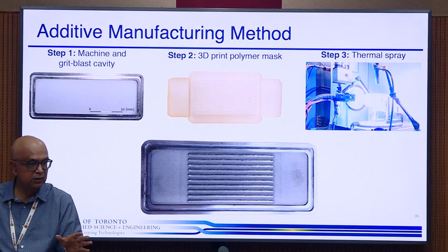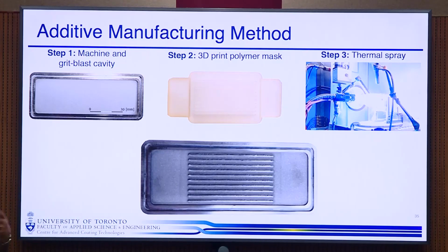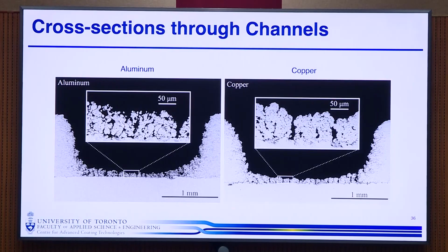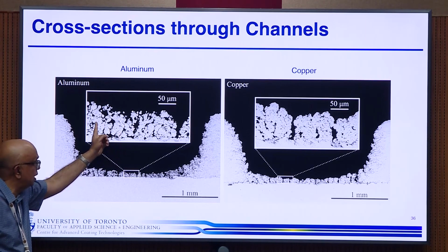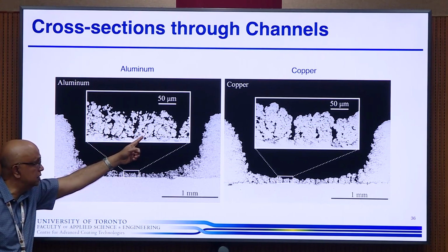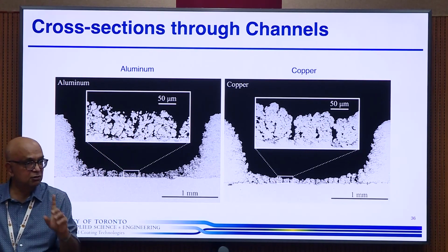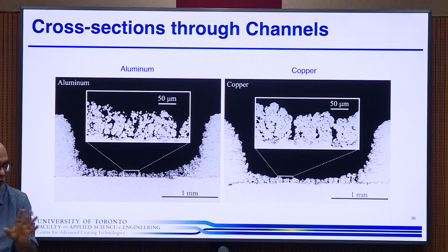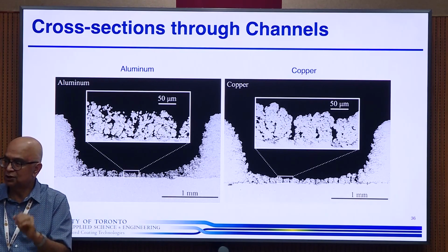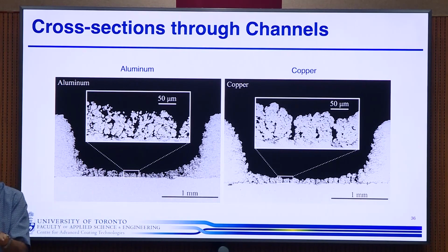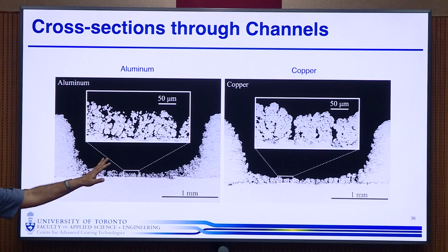So we've sprayed this out of aluminum. We sprayed one out of copper. And if you see the section out of the aluminum and copper, and you actually focus in over here, this is actually a great boiling surface. People spend a lot of time trying to make porous surfaces. They use femtosecond lasers to make new nucleation sites. We just, by the process, get a great set of nucleation sites.